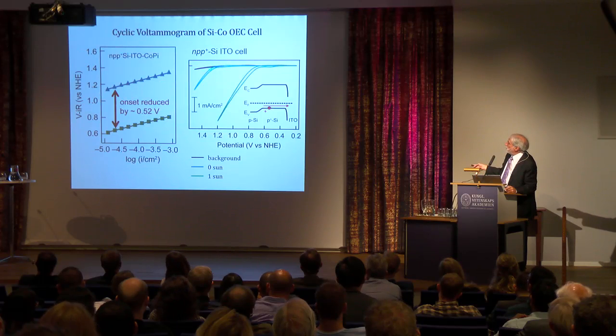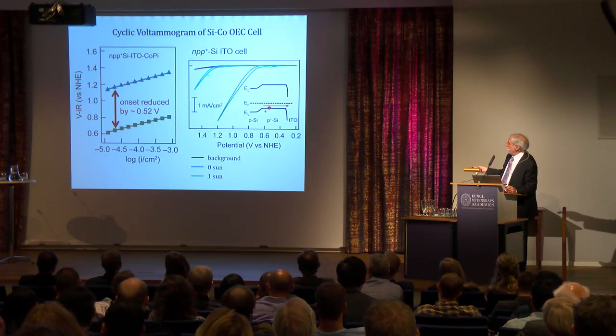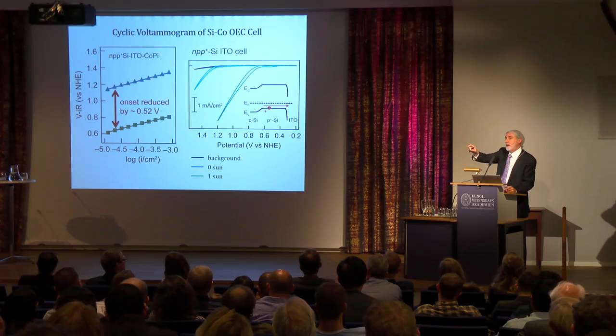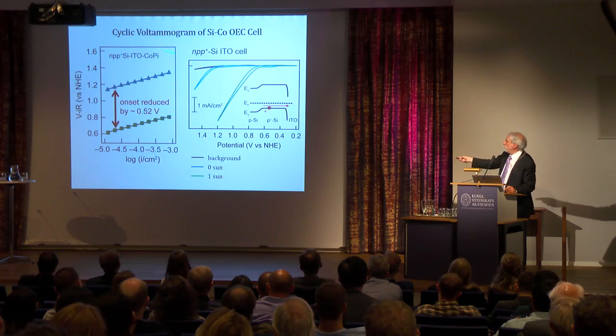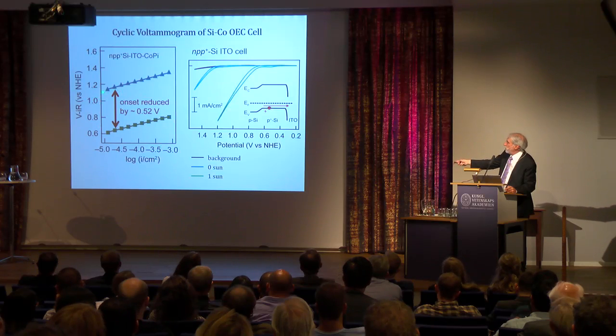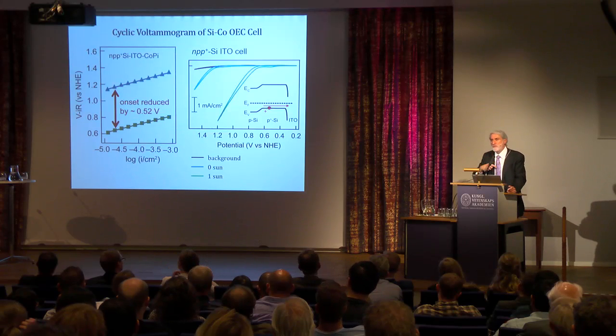So now, when I take that electrode in the dark, it takes 1.2 volts to start splitting water. When I now put it in sunlight, I don't have to push it as hard. As a matter of fact, you can see at any driving voltage I use on the silicon, once sunlight is shining on it, I reduce the amount of extra voltage I need to put into the silicon by 0.5 volts. So now you can start thinking, well, if that's what one junction does, what happens if you string a few of them together? And that's what we did.